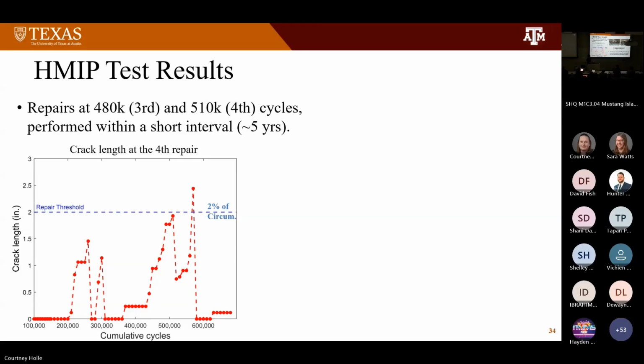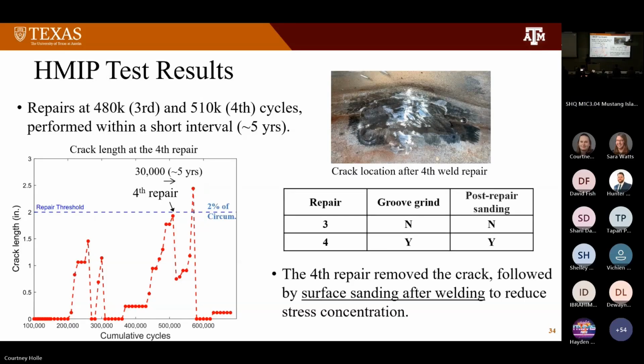So we decided to conduct the fourth repair just 30,000 cycles after the third. What set this repair apart from the earlier ones is that we sanded the weld surface after welding to minimize the stress concentrations. And since the metal in this location has undergone considerable fatigue, the new crack reappeared shortly after.